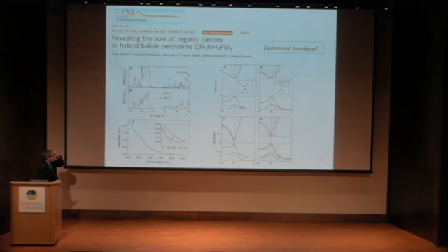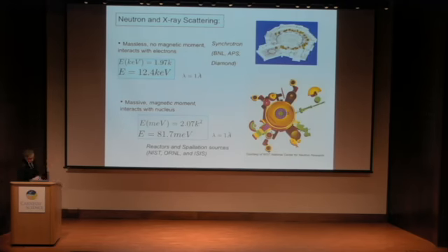So based on this, it seems to make sense to try to get a handle on what the phonons are doing and what the energy scale of the molecular framework is. Now, I think in this context, neutron scattering can play a really strong and important role in providing information. I think that for basically two reasons. One, first of all, neutrons, when they're produced from reactors or spallation sources, have a typical energy scale of something like 25 meV. And it turns out, because the neutron has a mass, that energy scale comes with basically the right wavelength that matches real materials that we want to study in particular.